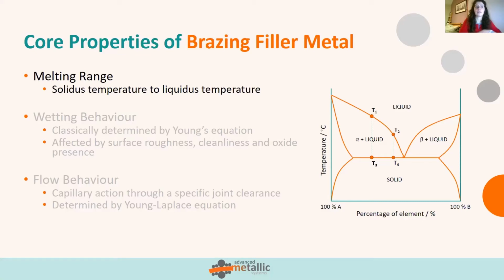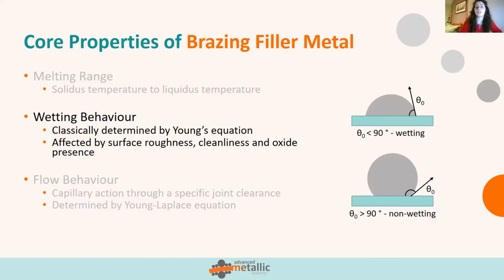The next of these core properties is the wetting behavior, and this is classically determined by the Young's equation, where an angle less than 90 degrees is wetting, which is what we want, and an angle greater than 90 degrees is non-wetting. You need to have a positive interaction between the material and the filler metal to ensure wetting, and therefore to ensure that a joint is formed.